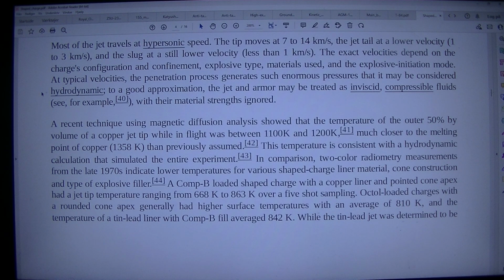To a good approximation, the jet and armor may be treated as inviscid, compressible fluids, see, for example, [40], with their material strengths ignored. A recent technique using magnetic diffusion analysis showed that the temperature of the outer 50% by volume of a copper jet tip while in flight was between 1100 K and 1200 K [41], much closer to the melting point of copper, 1358 K, than previously assumed [42]. This temperature is consistent with a hydrodynamic calculation that simulated the entire experiment. [43]